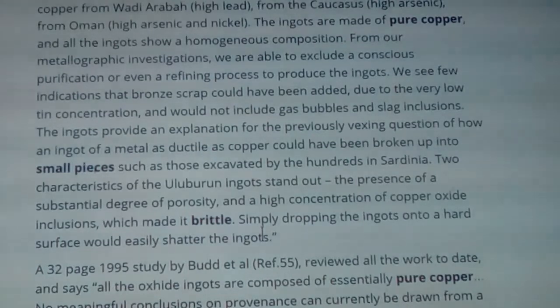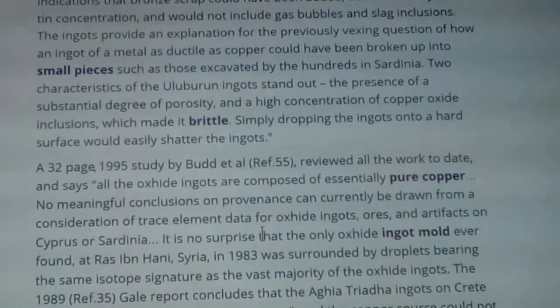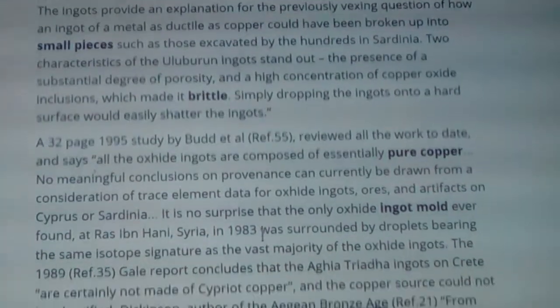The ingots provide an explanation for the previously vexing question of how an ingot of metal as ductile as copper could have been broken up into small pieces, such as those excavated by the hundreds in Sardinia. Too substantial a degree of porosity and a high concentration of copper oxide inclusions make it brittle. Simply dropping one of those big ingots on a hard surface could have made it shatter into pieces.